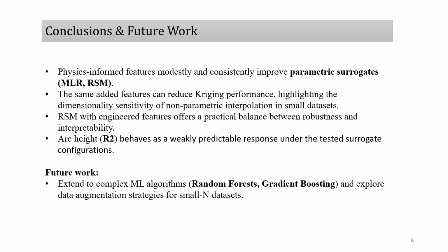To conclude, the results show that physics-informed feature engineering can improve surrogate modeling, but the effect is model dependent. The engineered features modestly and consistently improve the parametric models, especially MLR and RSM. This suggests that simple physical transformations of the input parameters can help these models capture part of the morphing behavior. However, the same features do not improve kriging and can even reduce its performance. This highlights an important limitation in small datasets. Adding more dimensions is not always beneficial, especially for distance-based or interpolation-based models.